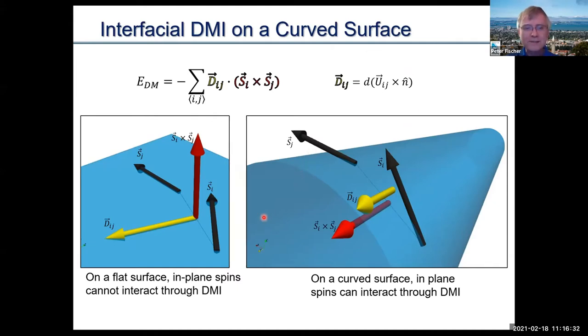So, for instance, on a flat surface, I want to repeat it, in-plane spins cannot simply interact through DMI because there is no DMI, but on a curved surface, these in-plane spins can interact through what I call a curvature-induced DMI. So this is a completely new way of playing with the spins and creating new structures and new spin textures.